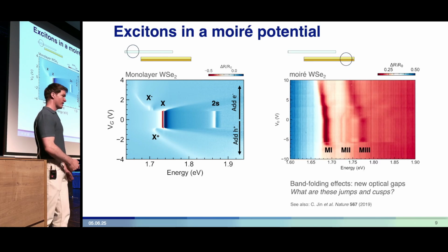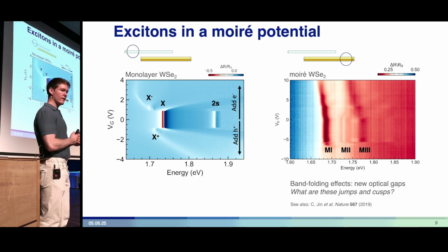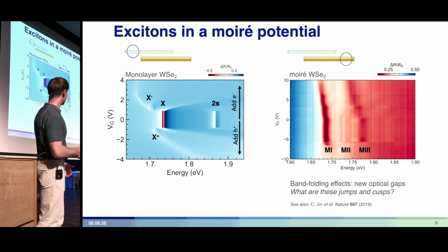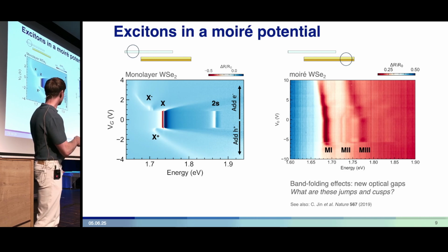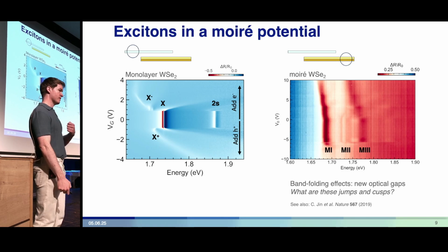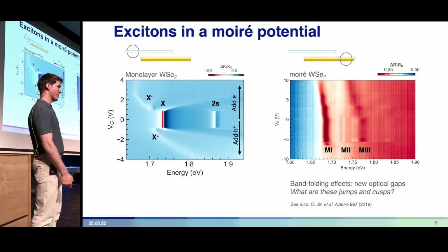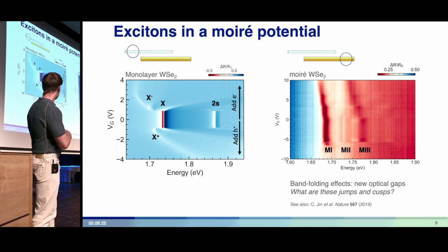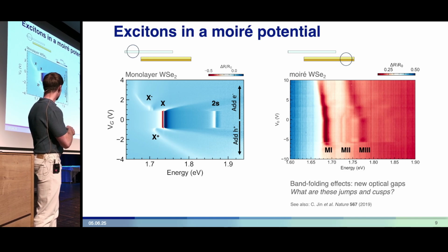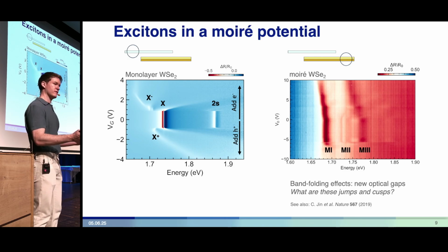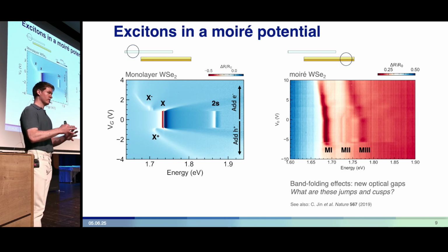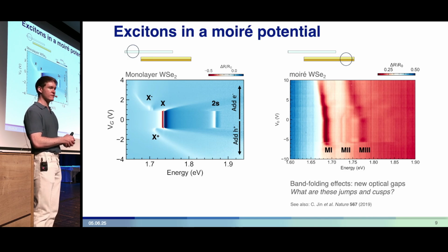On the other hand, if we look at the contributions of the WSe2 excitons to the Moiré heterobilayer, looking where we just have the Moiré system, no monolayer, but the spectral region corresponding to excitons in the WSe2, we have a very different spectrum. Instead of a single ground state exciton resonance at charge neutrality, we have 3, because we have a new periodicity in the system, which causes band folding and the emergence of new optical transitions.